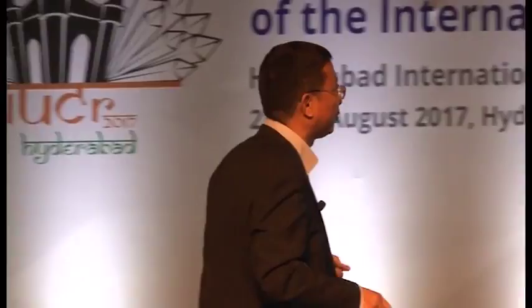Nitrogen is a diamagnetic molecule. But for oxygen, due to the two unpaired electrons, oxygen is magnetic. So the magnet can attract, in principle, the oxygen. This experiment shows we are using a magnet and putting it into the liquid oxygen, and you can see the magnet can attract some liquid oxygen. So oxygen is paramagnetic. At the same time, for nitrogen, if we put the magnet into the liquid nitrogen and take it out, nothing can be seen. It's diamagnetic.